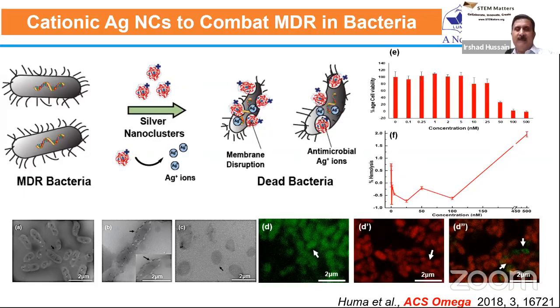And for that purpose, we have been designing different kinds of nanoparticles, especially silver nanoparticles, and trying to control their surface chemistry. For example, in this case, we prepared these 2 nanometer silver nanoclusters, which were positively charged due to the presence of positively charged polyethylene imine, PEI polymer. So these PEI-coated silver nanoparticles were really useful to kill different uropathogenic strains, which were otherwise difficult to kill with different antibiotics. So they were basically multi-drug resistant. But in the presence of these cationic silver nanoclusters, we were able to kill about, I remember, 12 different uropathogenic strains, which were multi-drug resistant.